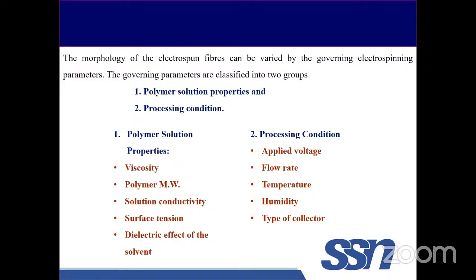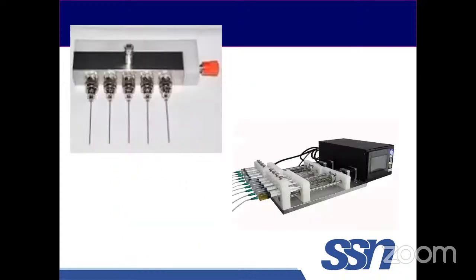So by playing with these two sets of process parameters, we can tune the fiber size that we actually need, right? Basically it's a trial and error process. We have to play with these parameters and do the SEM analysis in order to identify, for a given parameter set, the fiber size that we are obtaining. So by playing with these parameters, we can prepare nanofibers of a specific diameter based on our need, right?